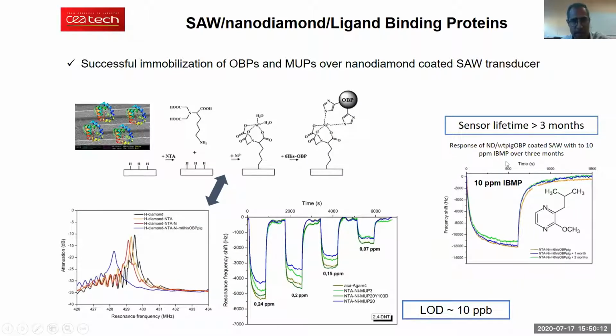I will not come back to this because I already explained how this works in the previous slide. We use the same approach to immobilize odorant binding proteins and MUPs on the surface of these transducers. We're looking at the resonance frequency of our device. This is a resonance peak. As we add the different functions on the sensors, we have a shift towards lower frequency because we are adding mass loading on the surface. But after the last step of immobilization of the proteins, we can see that we still have a very nice signal. So we can now start to expose our sensors to different odors, different VOCs.